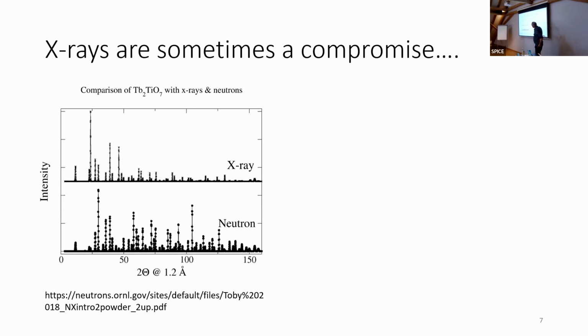And so this is an example of this material studied with the exact same wavelength with X-rays and with neutrons, which I copied from this PowerPoint from, I think it's Oak Ridge. And you can definitely see that because of the cross-section of X-rays compared to neutrons, it's harder to study this material than it would have been with neutrons because of this decay in intensity with the ordering wave vector.